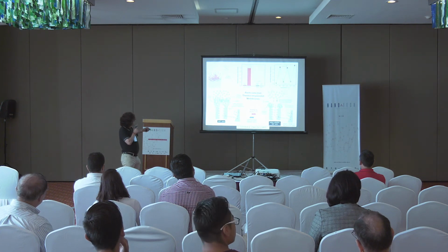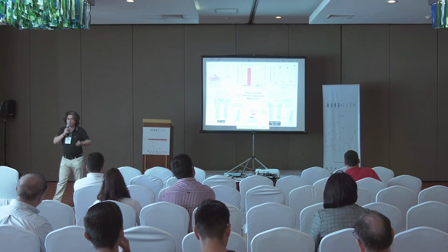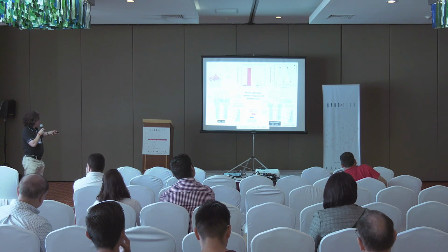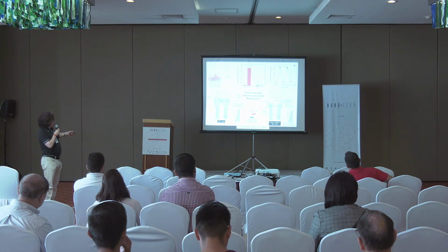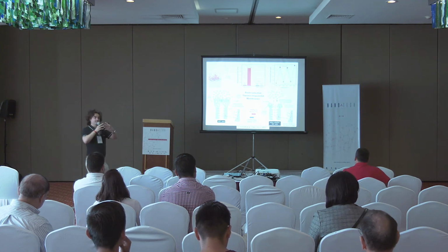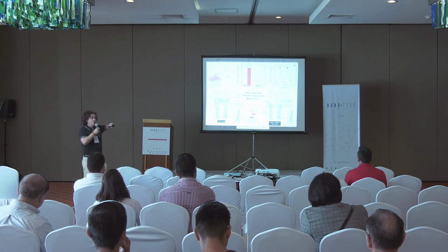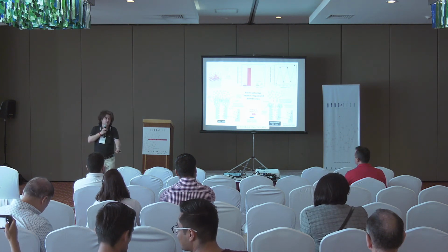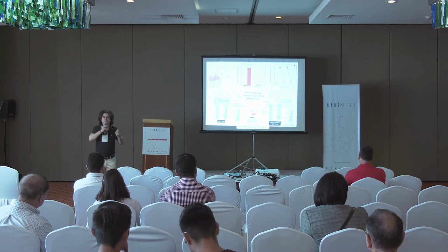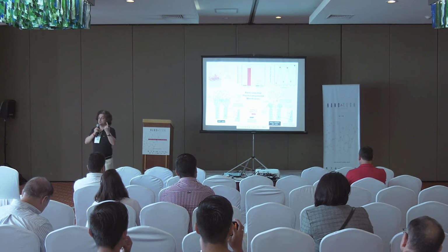You can put a thermoresponsive polymer here. NIPAM is a very well-known polymer. We can put it on top of the surface and not inside the pore using another strategy. And what happens here? At a low temperature, NIPAM is hydrophilic. So it makes a kind of microgel on the surface and blocks the pores because it's a microgel. Molecules will not go in. It's too dense, too thick. But at a higher temperature, this NIPAM gets hydrophobic, expels water, collapses, and opens the pore. So it's a temperature signal.